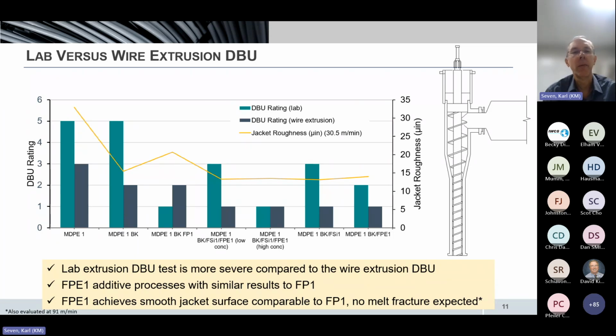One thing that we saw was that the lab die buildup test was more severe overall, whereas the full-scale extrusion process was a lot more forgiving in terms of die buildup. And so the lab scale test was more useful for these initial screening experiments than what we found with the full-scale wire extrusion line.